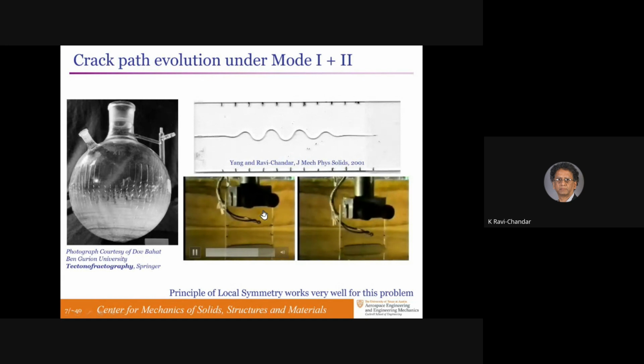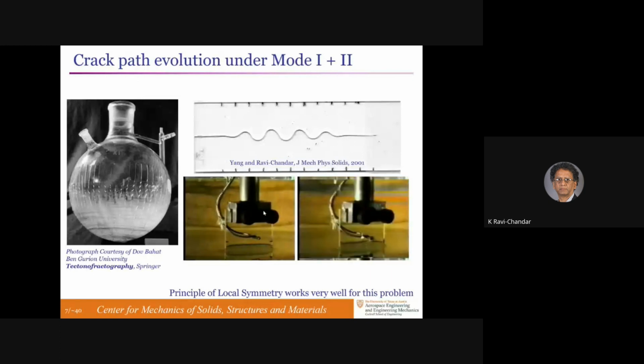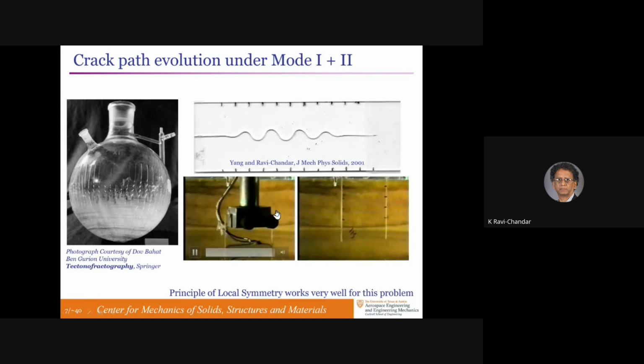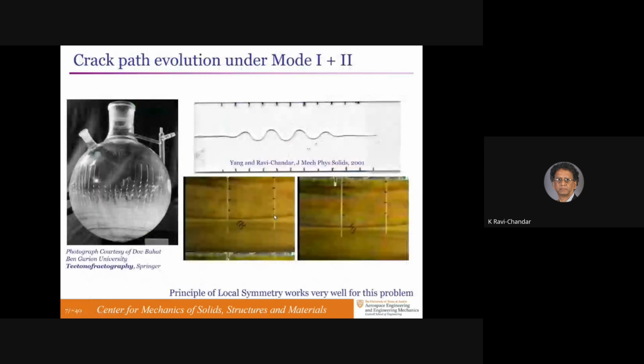These videos were taken about 15, 20 years ago. Technology was not very good at that time. You could see a very nice sinusoidal oscillation on the right side, and the left side, the crack was straight. And the criterion that I posted in the previous slide, any one of these criteria would be able to predict that oscillating crack very easily without any difficulty. So the mode 2 problem, I think, is also a well-solved problem, doesn't need much more attention.